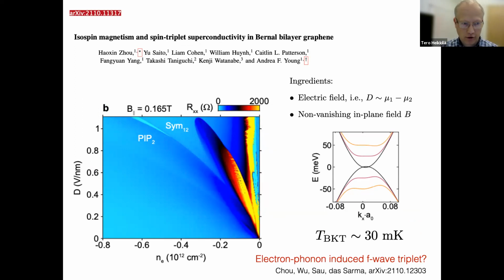Bilayer graphene was studied already in the early days of graphene quite a bit. Those who were there may remember that the bilayer was used to prepare field effect transistors from graphene, because what was told was that graphene's problem is the fact that there is no gap. So it is hard to make logic elements because the conductance is always finite. But with bilayer graphene, people managed to make gaps by applying this electric field inside, and this is what actually happens in the system. So you have different Ds here, and you have the bilayer spectrum. Starting from this quadratic touching, you go to this gapped phase.